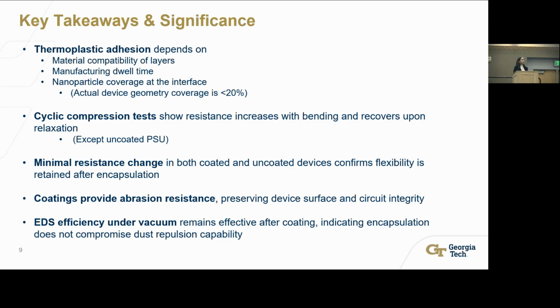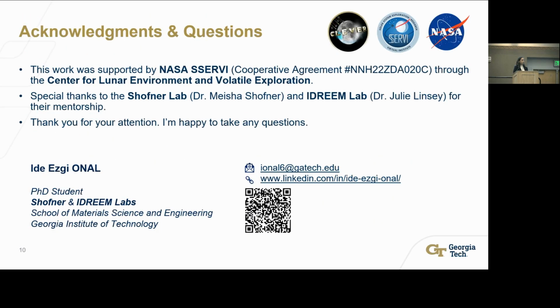And we've also seen our coatings providing some abrasion resistance as well. So the device is being protected against the external stress factors, which was mainly the dust in this case. And finally, with the EDS efficiency under vacuum, we've seen that the performance has remained effective even after the coating was applied. So this indicates that the encapsulation does not mainly compromise the dust repulsion capability. And it's also gotten rid of the dielectric breakdown or arcing problem that my colleague Luca pointed out before. So we improved our design with this encapsulation layer.